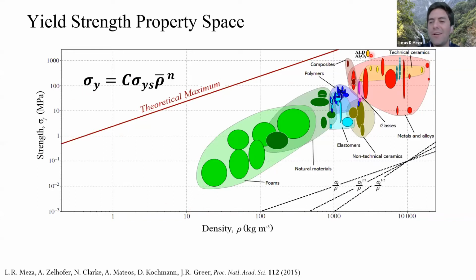Here's that density versus strength. You'll notice here at the top, this yellow bubble is ceramics. Here, that ALD alumina, ALD Al2O3, this is the material we were using. It has yield strengths on the order of 2 gigapascals, much higher, especially in tension, than a normal bulk ceramic would be.